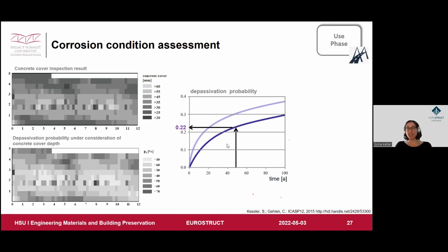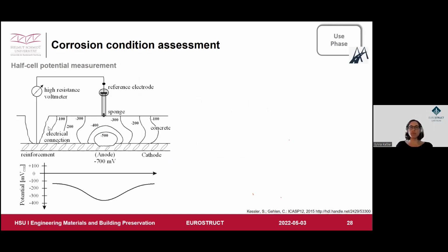Here the asset owner decided it's a little bit too high, so he did some further inspection, and as I mentioned, the half cell potential measurement, which I would like to explain very briefly, gives you just the information you need to know. Here you need to connect a voltmeter with the reinforcement, so you partly have to destroy the concrete in order to get the electric connection. Then you have a reference electrode, which measures the half cell potential between the reinforcement and the reference electrode. And as soon as we have a corroding spot, the potential is much lower than at the cathodic areas in the neighborhood.